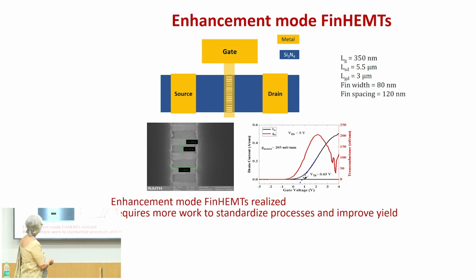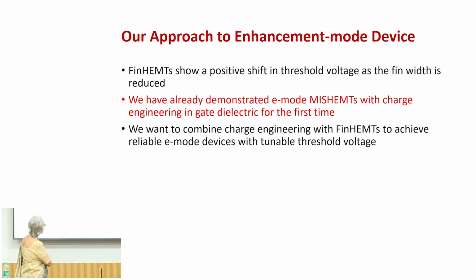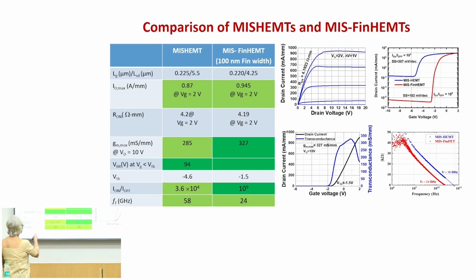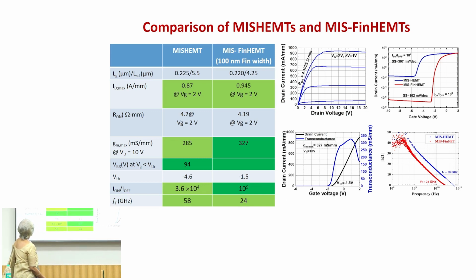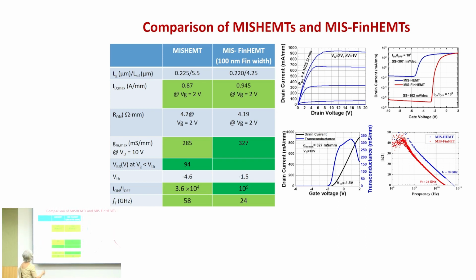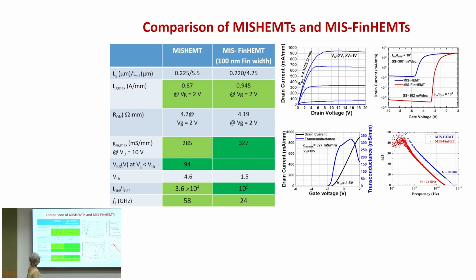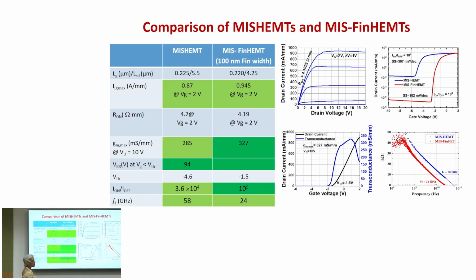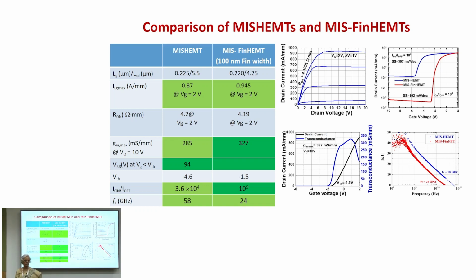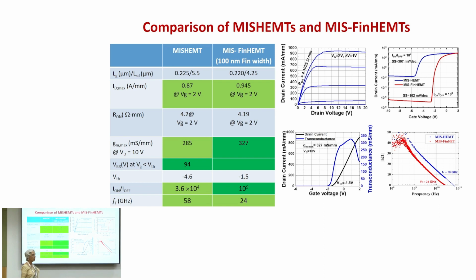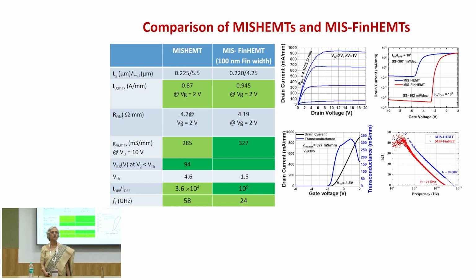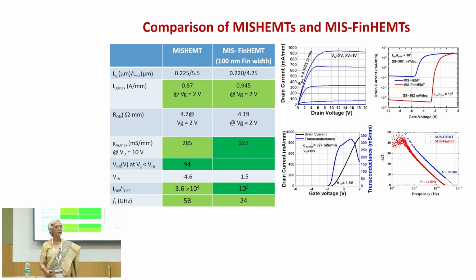If I can just go back for a moment, I wanted to tell you something. When I was comparing the MISHEMT and MISFinHEMT, as you can see here, the gate length of both of them is about the same, 225 nanometer, 220 nanometer. But just look at the threshold voltage, you find that while for MISHEMT the threshold voltage is minus 4.6 volt, for the MISFinHEMT it is actually shifted more towards the positive direction and it has got shifted to minus 1.5 volt. So, as I told you, the modulation in the threshold voltage is going to depend on the FinHEMT geometry.